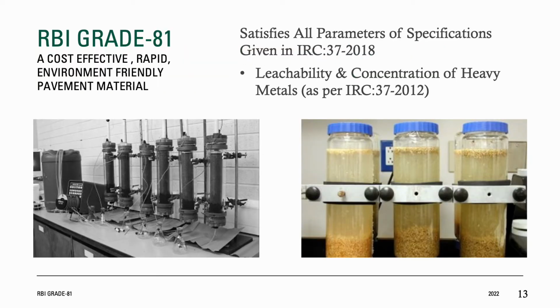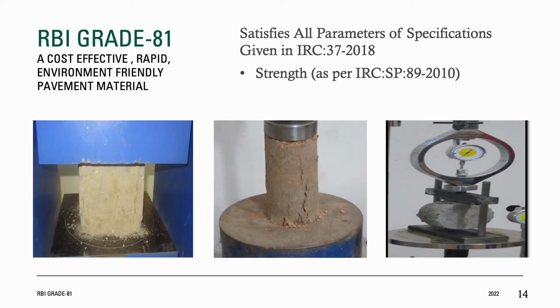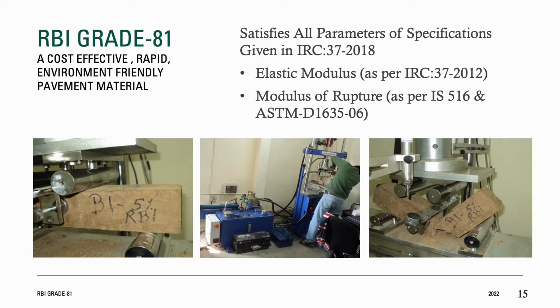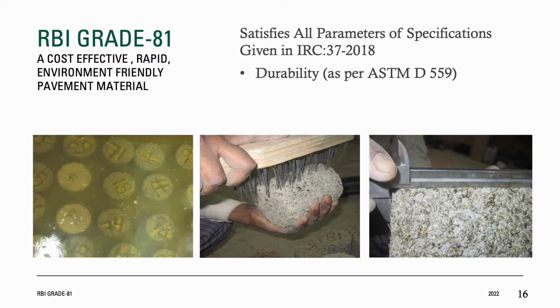Here, the material composition is being tested for the presence of heavy metals and their leachability. From left to right, UCS being measured on cubical specimen, UCS being measured on cylindrical specimen, indirect tensile strength measurements. The results are then used to calculate the modulus value of the composite material. For the direct measurement of the elastic modulus value of the composite material, we use beam specimens to test for their flexural strength and modulus of rupture. Durability testing for wetting and drying cycles.